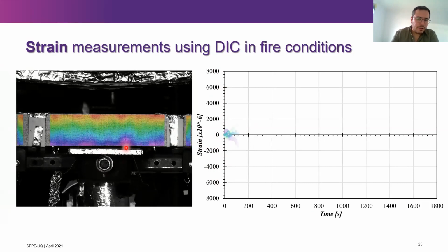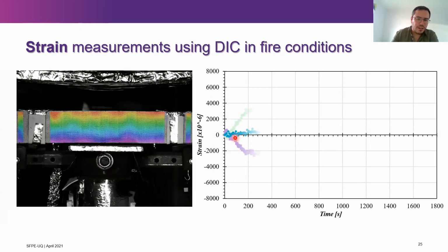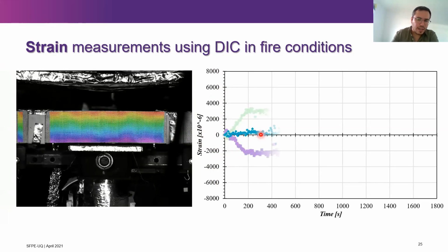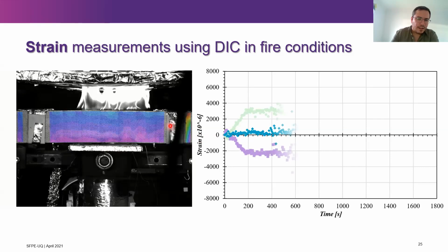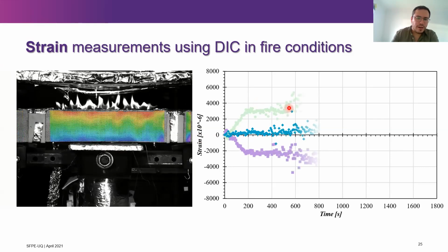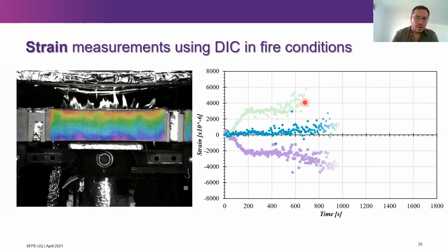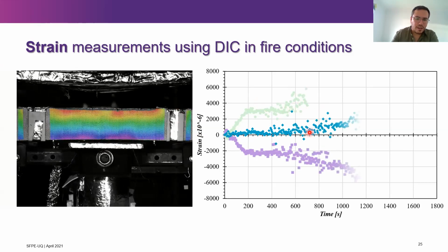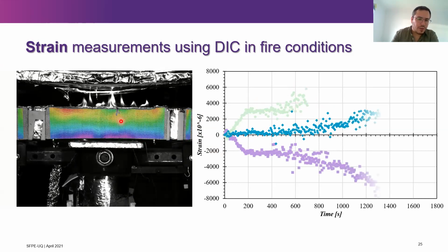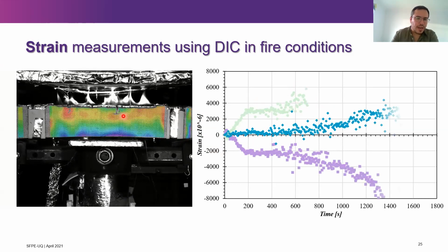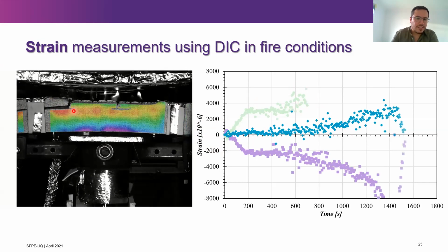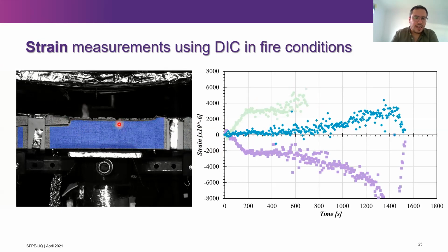You start loading the beam, you have compressions here, tensions here, right? Tension, compression, and the neutral axis where the strain is pretty much zero. And then you start burning the beam. Once you start burning the beam, you have more strain, because you start increasing the stresses, until you finally reach failure. What was really nice and really cool about this system is that you can see the fire propagation and you can anticipate where the failure is going to occur, because you can see which parts of the beam are subjected to higher strain and of course higher stresses.